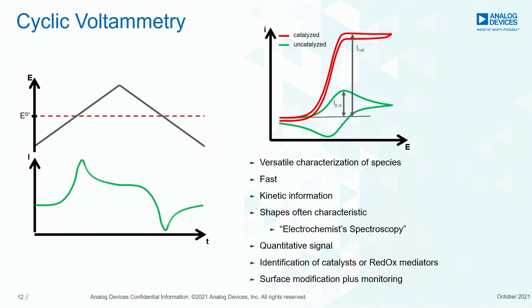This is a potentiostat in a nutshell, and I want to give you just 3 examples of popular electrochemical techniques to show you the variety that is there in electrochemistry. Cyclic voltammetry is what we've done just now. We made a linear potential sweep in a certain direction, and then, with the same slope, we just made the slope negative, so in the other direction, we swept our potential again. What you get is, over time, you see on the left the potential versus time, and then the current over time. When you get close to the potentials where reactions are triggered, you suddenly get an increase in current. What you then plot is the current versus the potential, which you see on the top right side,